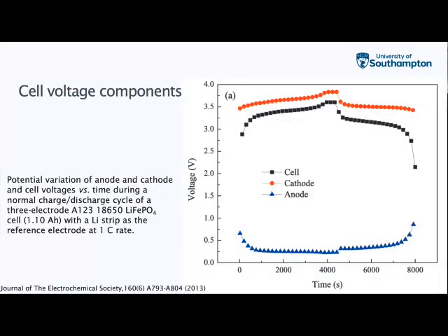We sort of mentioned the voltage losses and how the voltage profiles are built up for batteries. This is just an example of a charge and discharge profile for a lithium ion cell, an 18650 cylindrical cell, and effectively what you've got is the black line is showing the cell voltage during charging till it hits the voltage limit of just over 3.5 volts for the cell, and then it's discharging, and there's a gradual decline in the voltage until it drops off rapidly.